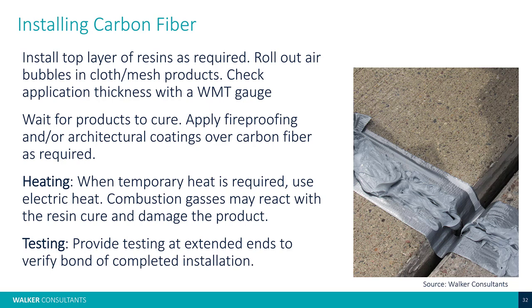Again, roll out any air bubbles and verify with the wet mil thickness gauge. Where you want to verify your wet mil thickness here is after the contractor gets it fully rolled in, to make sure that we've got enough product remaining over the top of the product. And then wait for the products to cure. Again, manufacturers are going to have a certain cure time. Cure is also dependent upon ambient temperature, ambient moisture, that type of thing. So this thing may kick off faster or slower relative to ambient conditions.